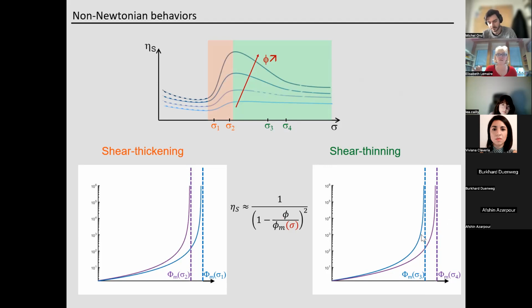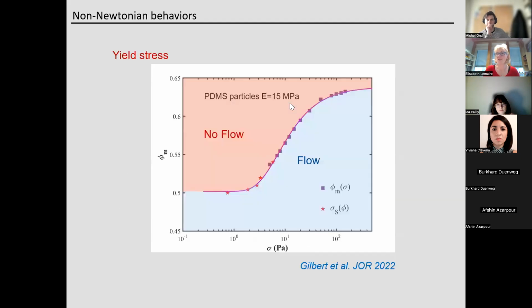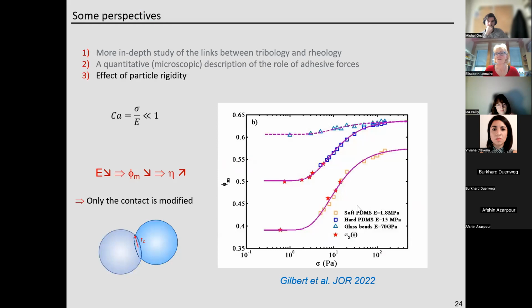So when you decrease the jamming volume fraction, then you increase the viscosity. Okay, so from this result, it means that when you decrease the rigidity, you increase the viscosity. And this is a little bit counterintuitive because one could have thought that when you decrease the rigidity, when the particles become more deformable, it facilitates the flow, but it's not the case.